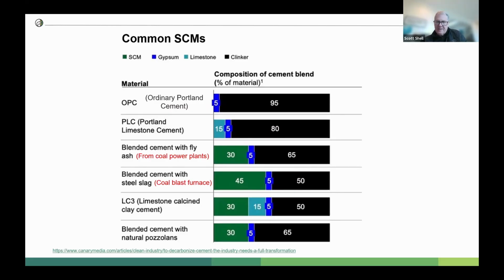So ordinary Portland cement at the top, that's 95% clinker. That's the really high carbon part, right? That's the part that releases all those process emissions in that chemical conversion. These other materials are very, very low carbon because they're more byproducts. So the slag and LC3 are at 50% clinker here. So you're almost halving the amount of carbon emissions when you make cement and concrete with these high replacement levels.